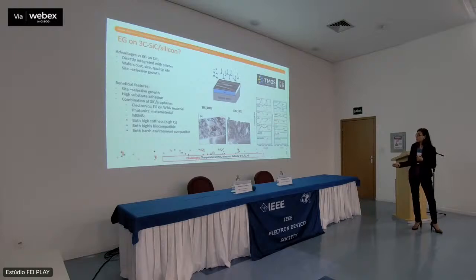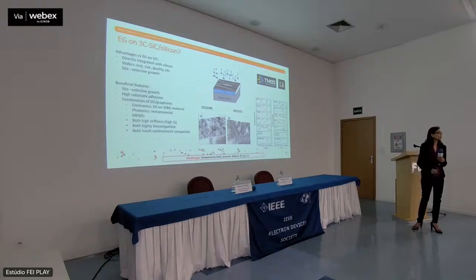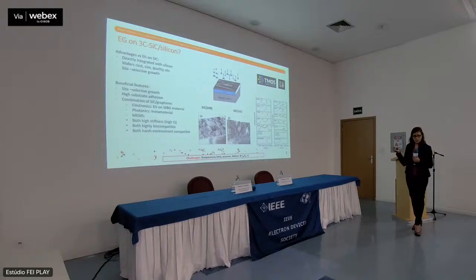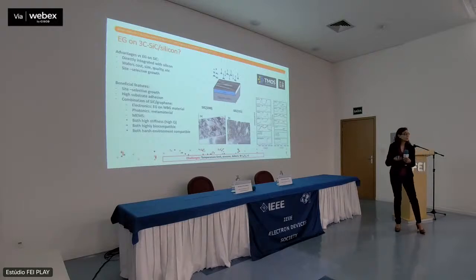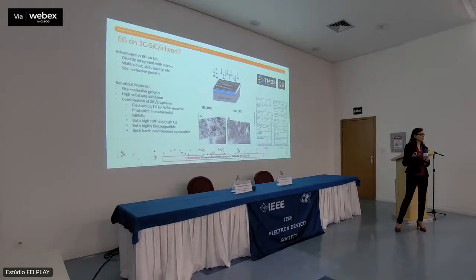The other problem is that we're working with silicon, and we can't go too close to the melting temperature of silicon. On silicon carbide ingots, this process in high vacuum really works best above 1500. So that's an additional problem. So yes, this doesn't work.